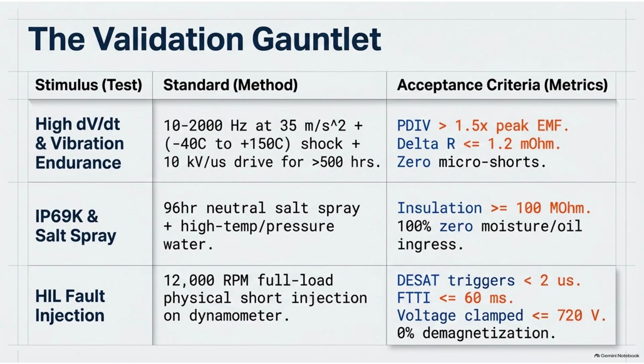Exactly. After surviving the salt spray and the pressure washing, they connect a high-voltage digital megohmmeter and hit the internal phase wires with 500 volts DC for 60 seconds. To see if any moisture got inside and compromised the insulation? Precisely. The insulation resistance must measure greater than or equal to 100 megohms, with absolutely zero microamp leakage to the ground. Then they tear the motor completely apart to physically prove there is 100% zero oil or moisture ingress inside the stator chamber. The insulation test proven right in the most brutal way possible.